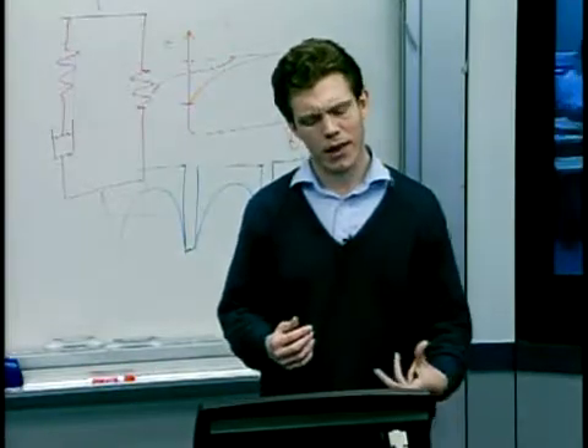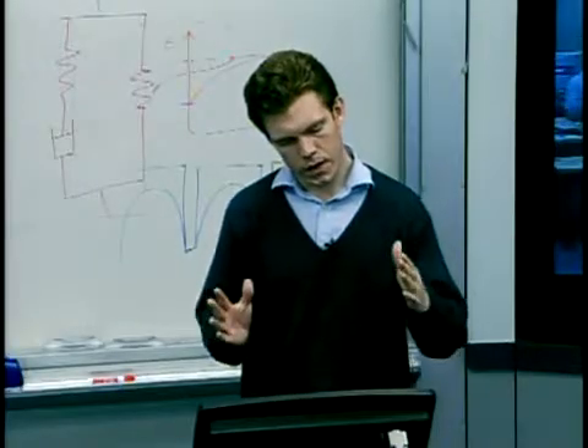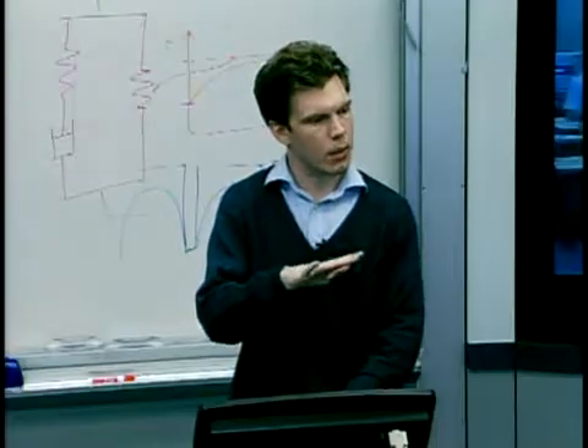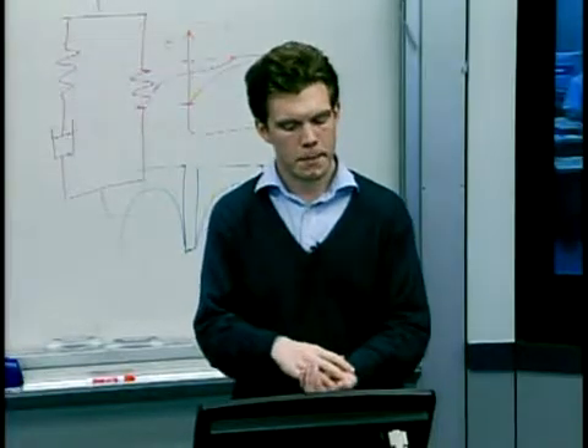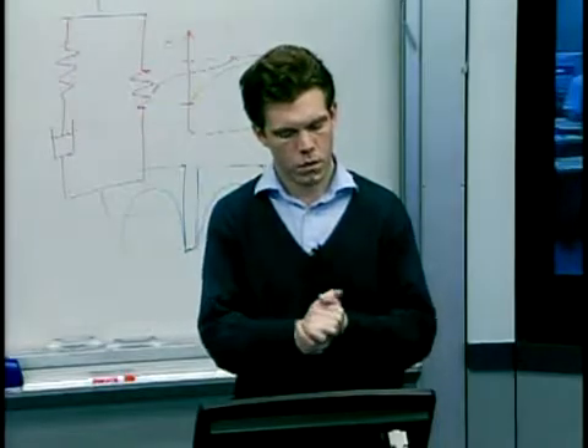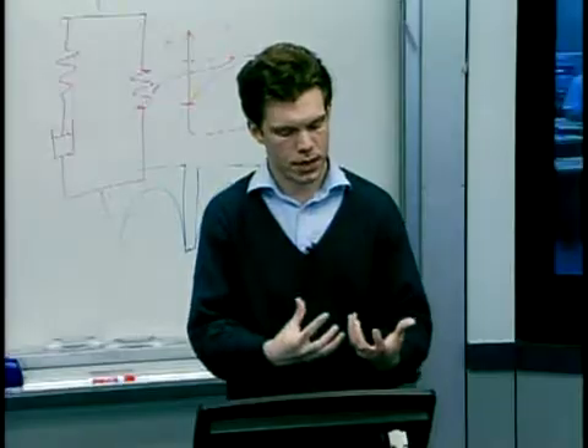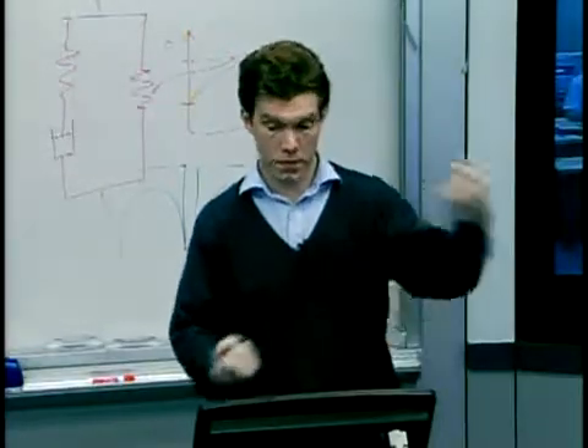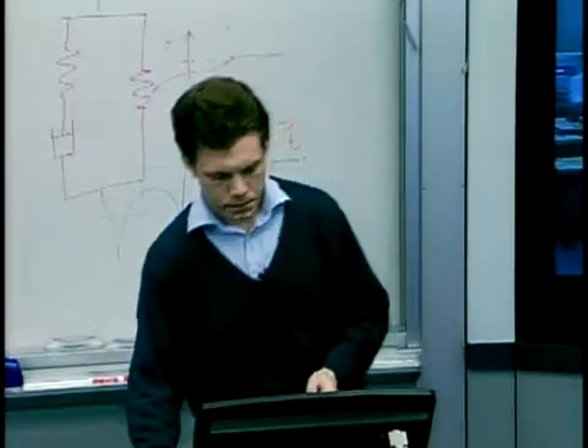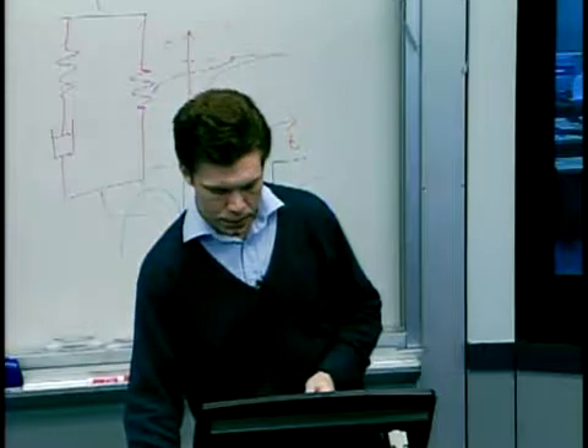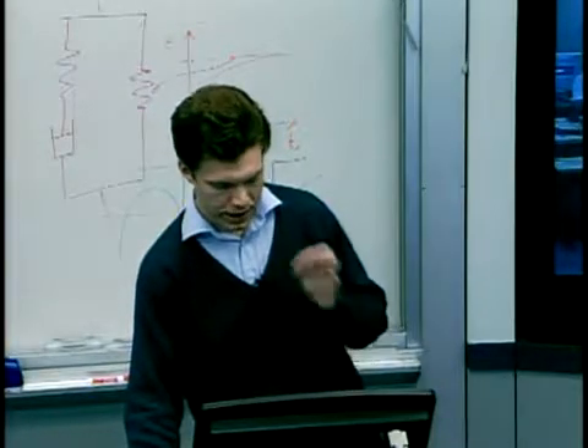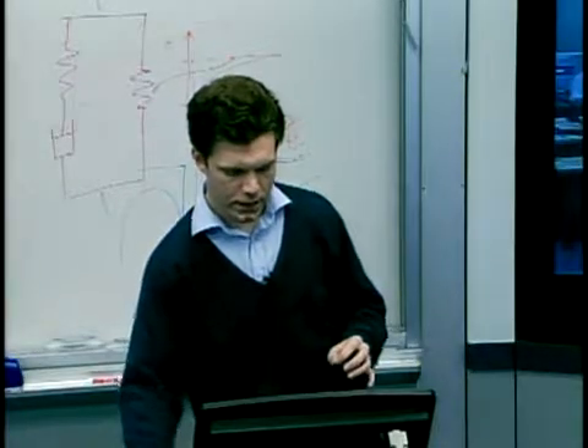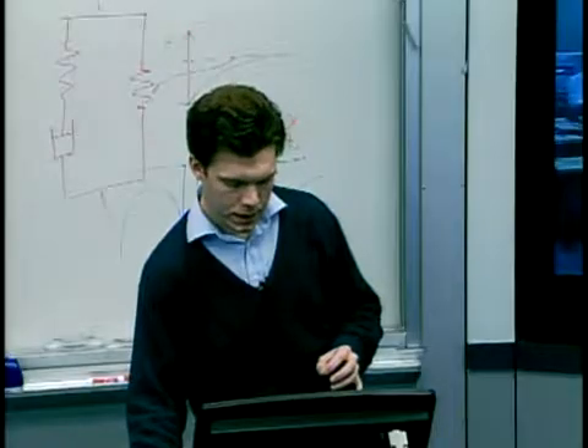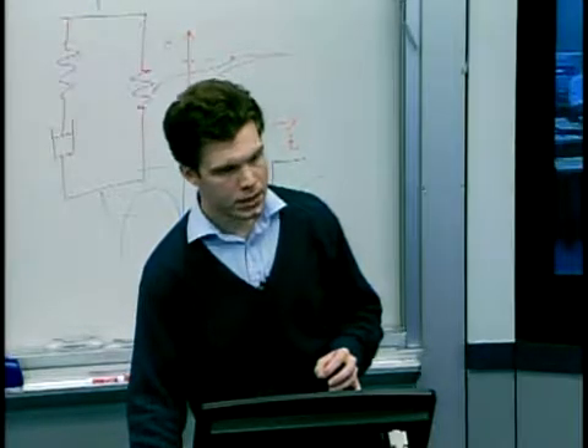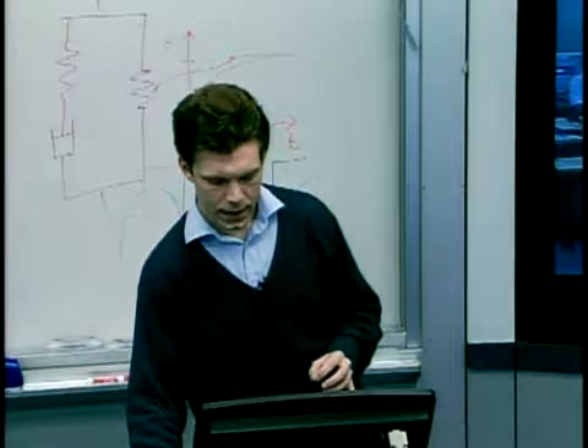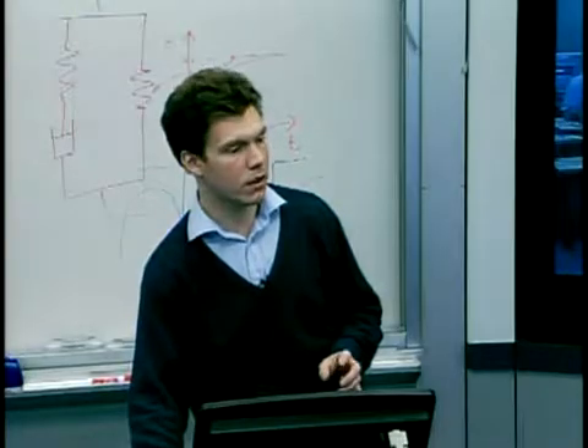What we haven't yet worked out is whether these contact stresses are large enough actually to push the stamp off the substrate, or whether it's just elastic potential energy stored in the polymer that causes this ridge to spring up when you peel the stamp off the substrate. Here are some optical micrographs showing a similar problem. A triangular hole embossed into a polymer substrate. The material is contracted from right to left relative to the stamp feature. In fact, sometimes we see these shards of polymer being sheared off. And again, a hole where there's been a few tens of microns relative contraction.